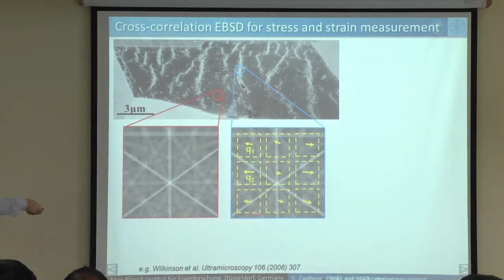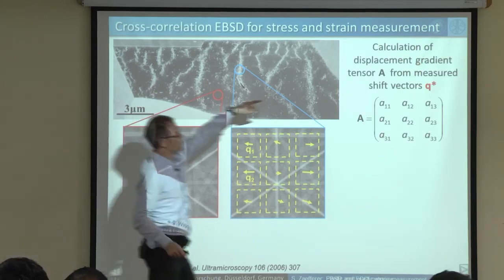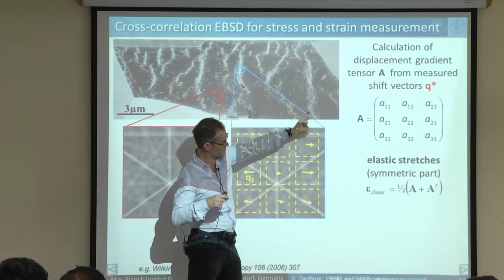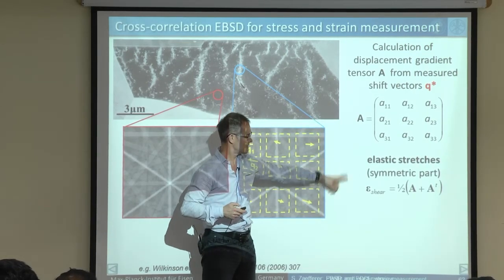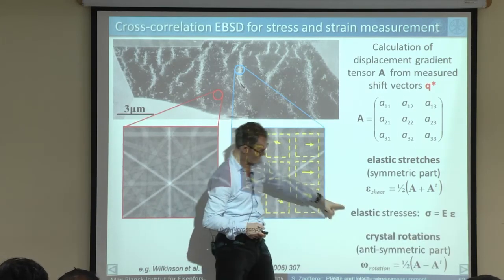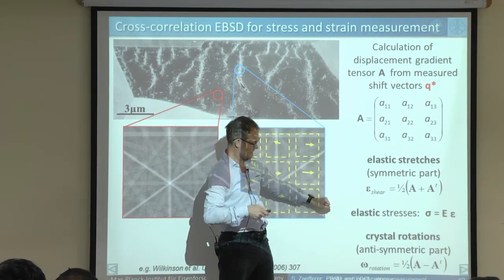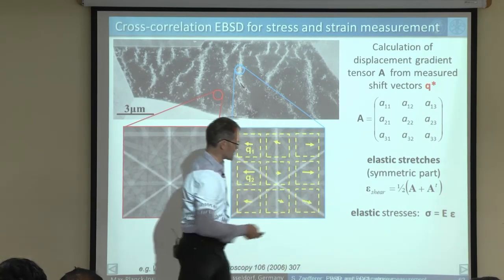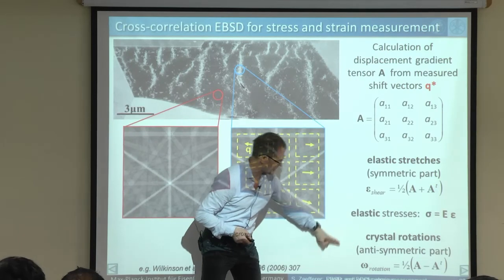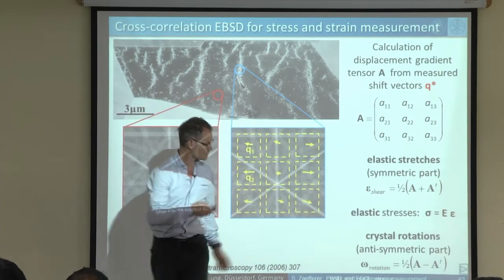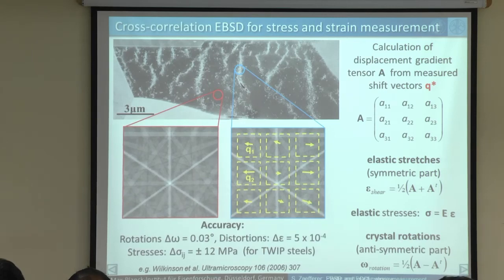And now from all these vectors Q, you're able to calculate what is the stress situation, what is the elastic strain first at that place which we are measuring relative to this place here. And we can then obtain from this the displacement gradient tensor, and from the displacement gradient tensor we can calculate the elastic stretches, which is the symmetric part of this tensor, and then of course the elastic stresses using just the stress equation here, and then the crystal rotations we can get from the antisymmetric part of this tensor. So applying that, we are able now to plot the stress and strain distribution with a decent accuracy.